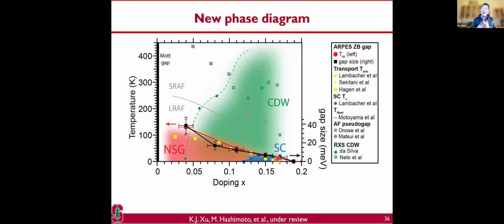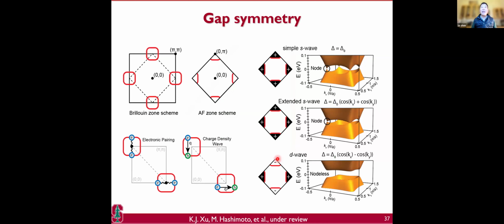Then I already used up the antiferromagnetism. I cannot use charge density wave. So there are very few options left. I should say, bypassing my colleague Bob Laughlin will say you've discovered a d-density wave. But now I'll take a more mundane view, and say that in fact we see the same piece of Fermi surface, and there's another gap. This work was really done by Donghai Li, and you can show that this gap should be isotropic. Indeed, we find it to be isotropic, and there's no node in this system.